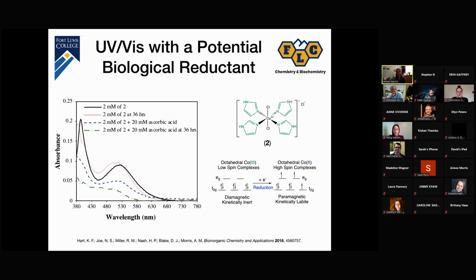we don't know for certain if this will become a high spin complex, but what we do know is if cobalt 3 does in fact become cobalt 2 in the presence of biological reductants, no matter if it becomes high or low spin cobalt 2, it will have unpaired electrons. And so while cobalt 3 is considered low spin d6, kinetically inert, diamagnetic, we know that if this undergoes reduction, you will get an unpaired electron. And that will become more reactive than the cobalt 3 parent compound from which it came.